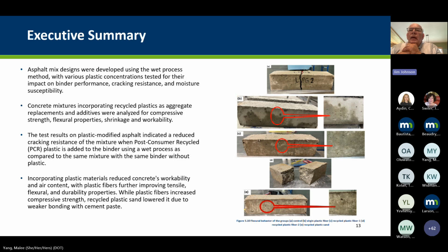Bullet number 2, concrete mixtures incorporating recycled plastics as aggregate replacements and additives were analyzed for compressive strength, flexural properties, shrinkage, and workability. And then quickly summarizing the results, the test results on the plastic modified asphalt indicated a reduced cracking resistance of the mixture when post-consumer plastic, which is not virgin material coming out of the plastic factories but material that is being recycled, is added to the binder using a wet process, as compared to the same mixture with the same binder without plastic. So there was actually a reduction in the performance in the case of the asphalt mix.